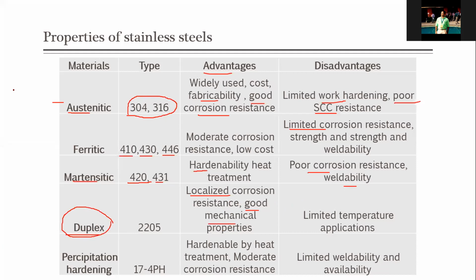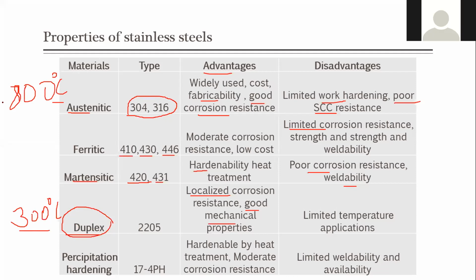Say the operating or service temperature of austenitic stainless steel is 800 degrees, whereas in the case of duplex steels, it is limited to 300 degrees. Above 300 degrees, we cannot rely on duplex stainless steel because there are various precipitations forming above 300 degrees centigrade in duplex stainless steel. Hence, this is the major limitation limiting duplex stainless steels over austenitic stainless steel. Comparing other properties, it has very good corrosion resistance because of enhanced chromium content in it.